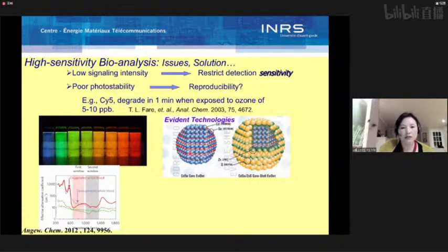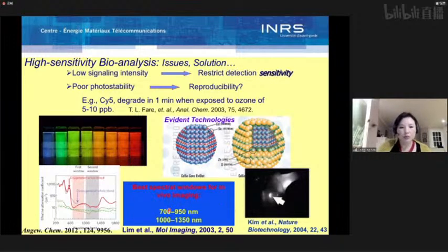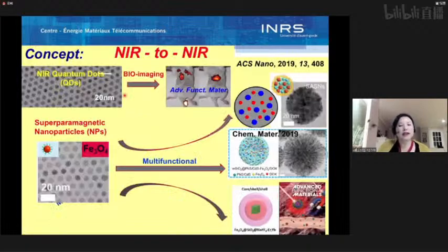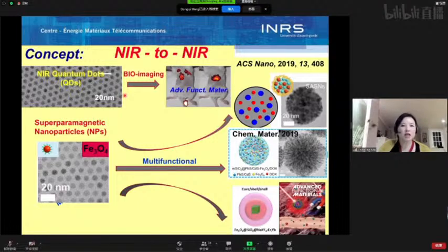Interestingly, quantum dots can be easily tuned to emit in the near-infrared range in these biological windows, which has been very difficult to achieve with traditional dye molecules. NAME's group has done careful theoretical and experimental studies and identified these two biological windows beneficial for in vivo deep tissue imaging: from 700 to 950 nanometers and from 1000 to 1350 nanometers. This was beautifully demonstrated by Kim's group in his pioneering work in 2004. They used near-infrared emitting quantum dots, I think in the first biological window, for photoluminescence imaging, which can be used to guide surgery in small animals. Because of that, we would like to work with quantum dots which can emit in the near-infrared, but also can be excited by near-infrared light.